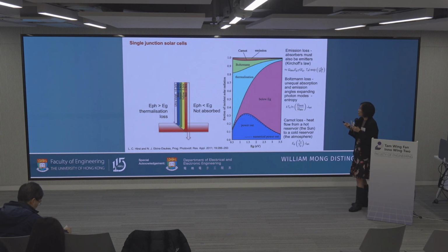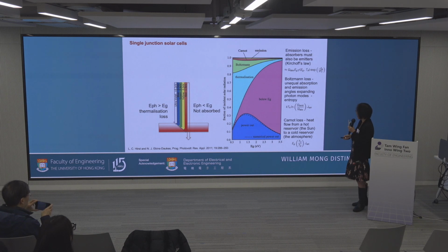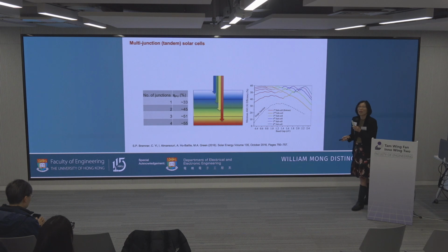People also ask me, can you have a 100% efficient module? Unfortunately not, because the solar cell is also an emitter, so you get the emission loss. You also get the emission angle loss, since there's a difference between the absorption angle and the emission angle. Then you have the entropy loss, and also there's heat flow from this hot sun to the cold environment, so you get that loss. So altogether, you don't quite get 100%.